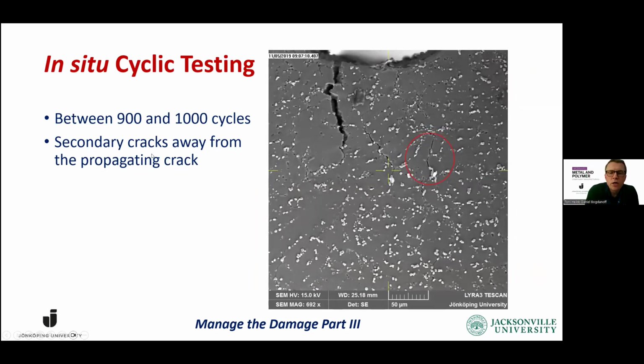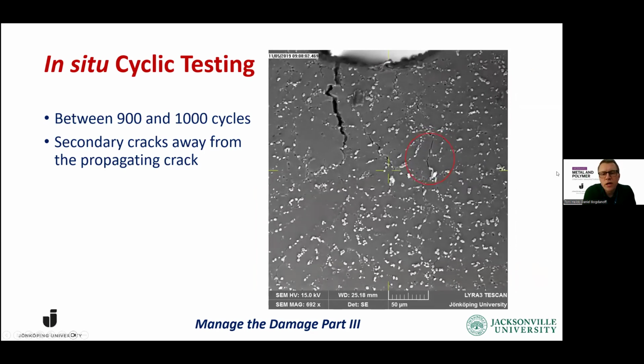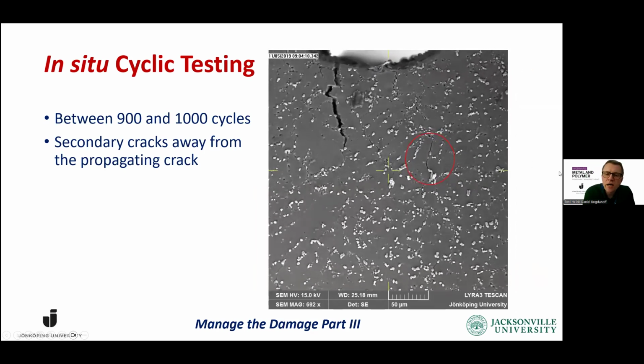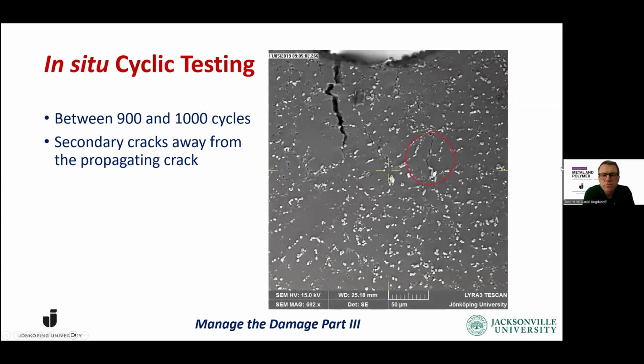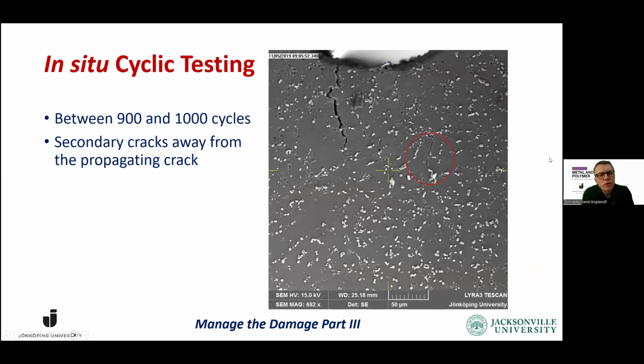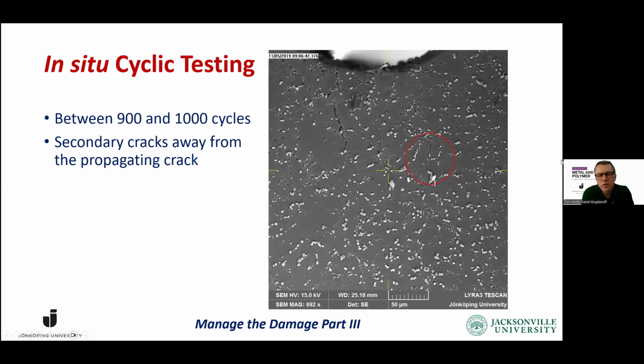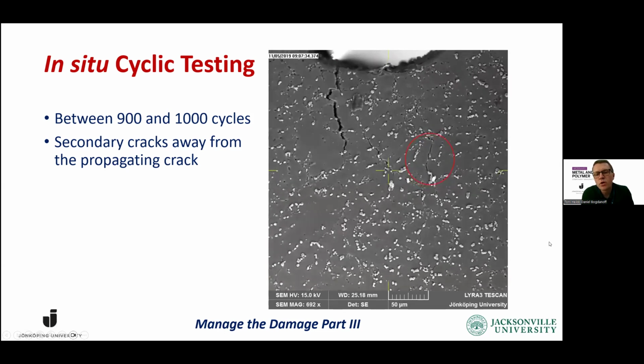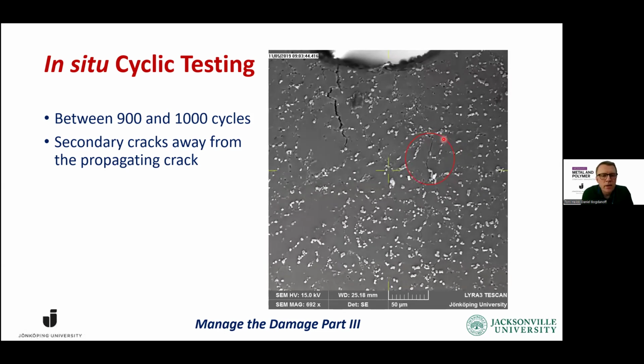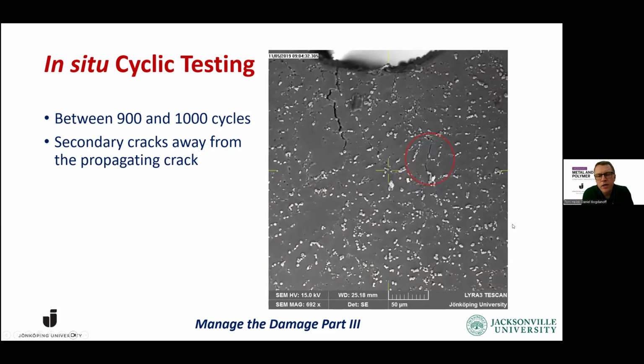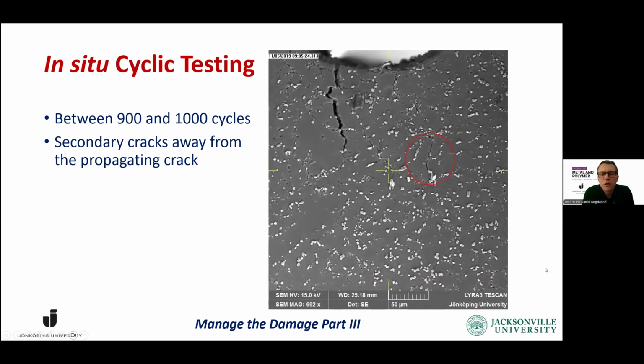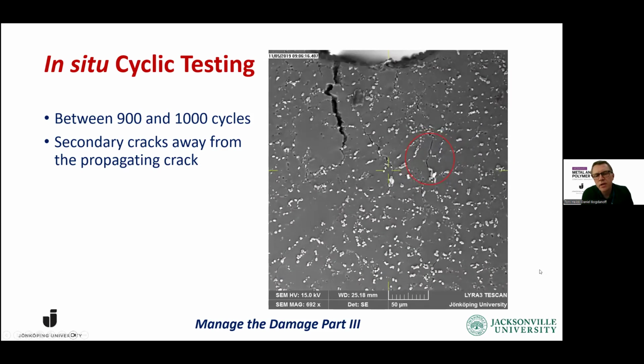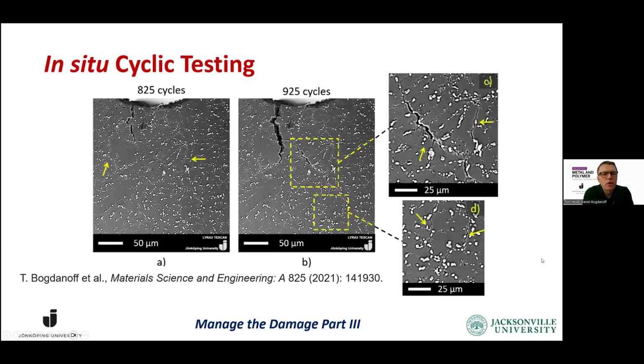Continue to this one, where we show how much hidden damage we actually have in the material when we look at this. We saw here between 900 and 1,000 cycles that we have a lot of small cracks opening up. And since we have our SEM and the focused ion beam, we can investigate what is happening in front of the propagating crack. So we decided to dig into this further in this paper that we published.